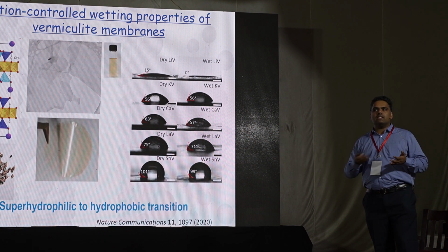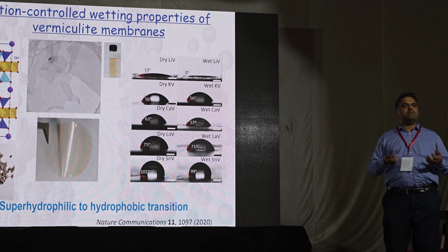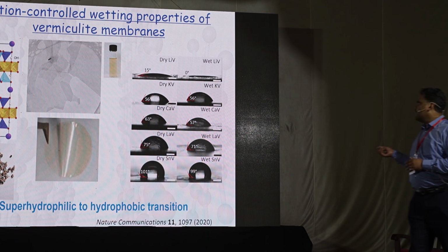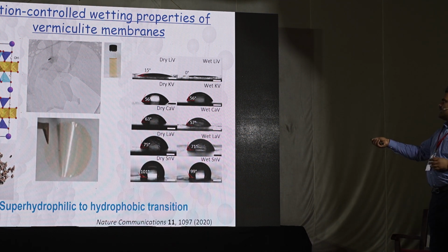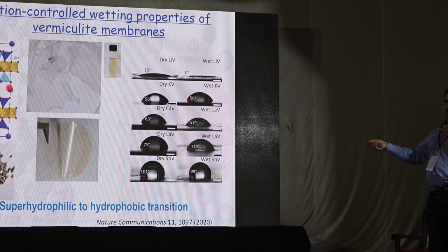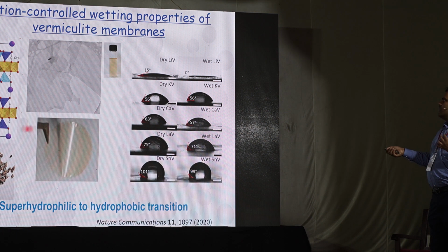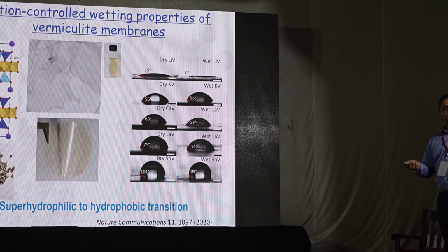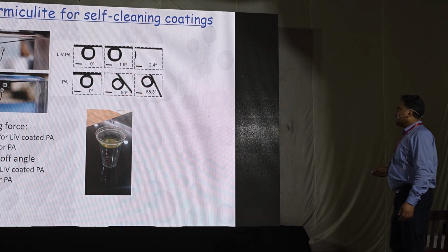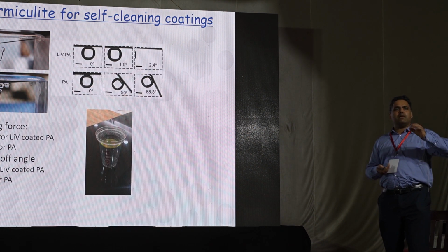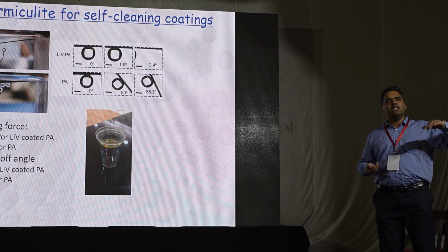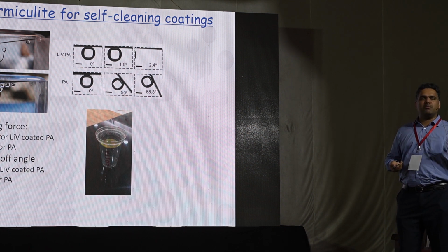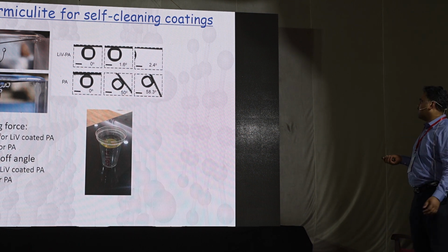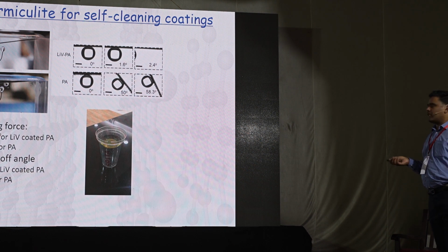We can tune the surface wetting property of this material by a simple technique. Basically, silicate has different layers of silicate with a layer of atoms in between, cations. By changing certain cations, specifically lithium, we get a super hydrophilic, basically super wetting surface. And what we found is that kind of surface, a monomolecular layer of vermiculite, we can use as a coating. It's not an active membrane, but it's a coating for reducing fouling in oil-water separation or emulsion separation and so on.